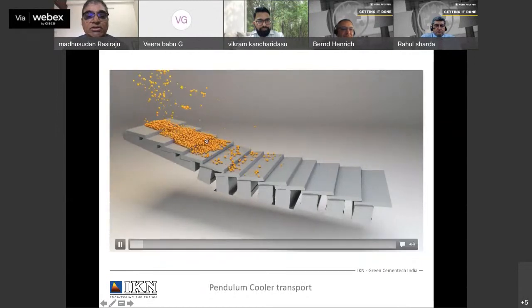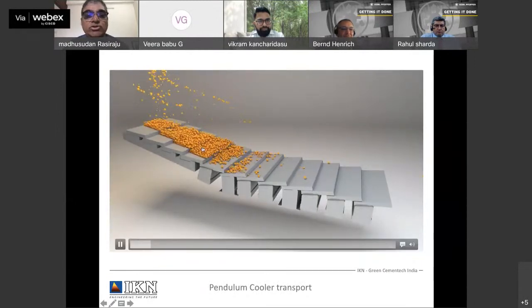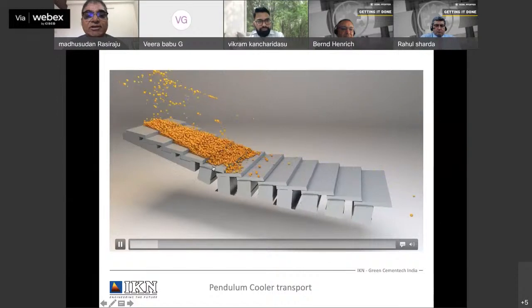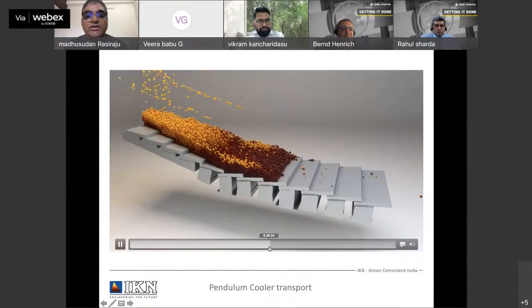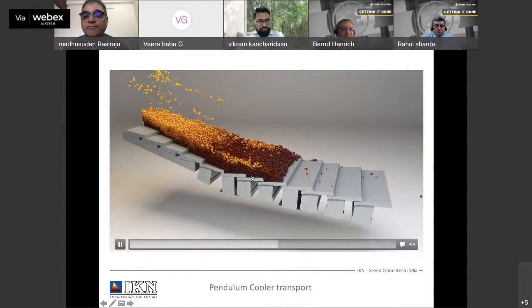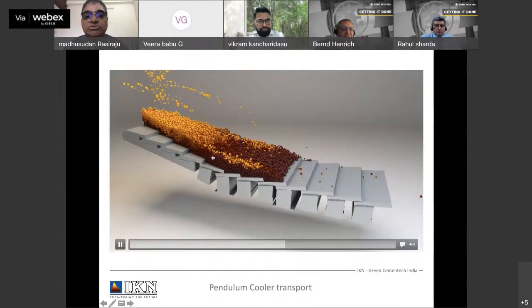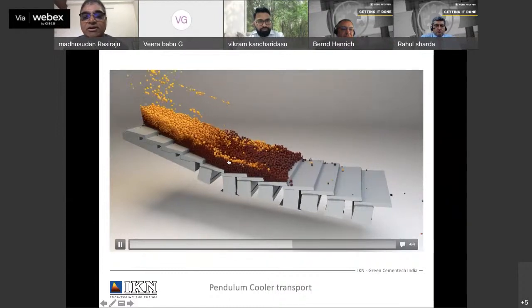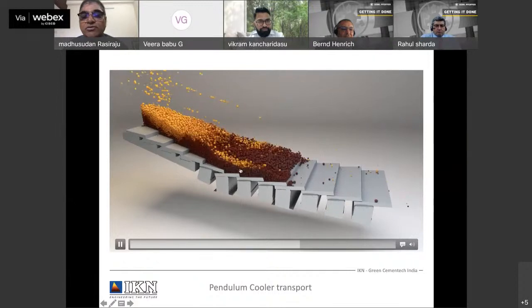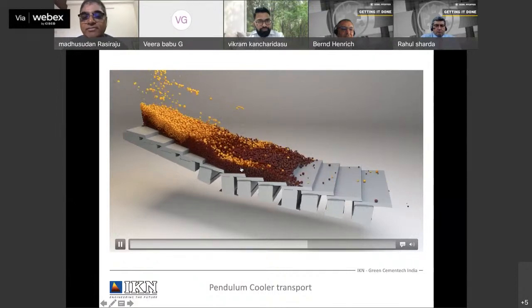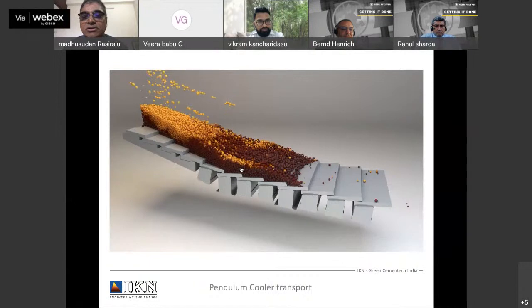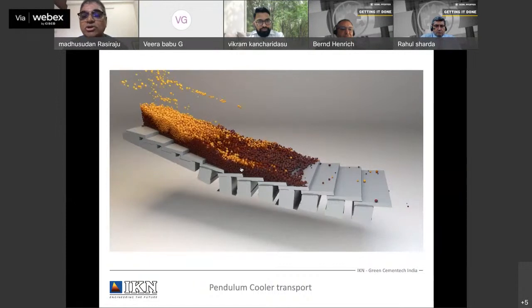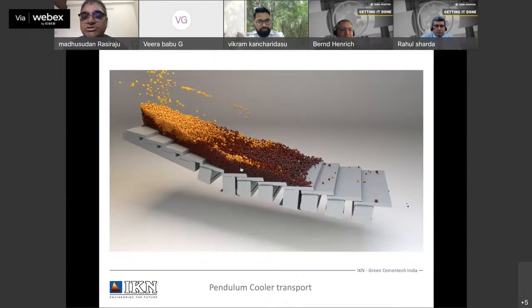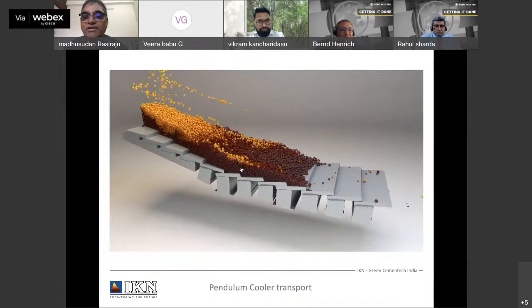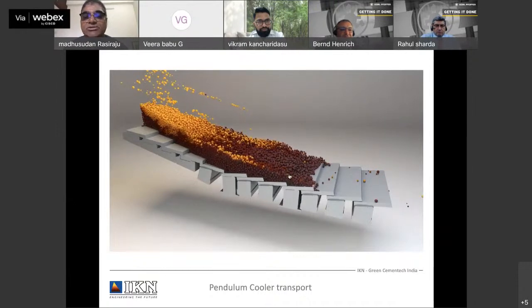And if you see here, the clinker simulation we have shown, on the fixed inlet the clinker comes in, and then when it comes to the movable section, the clinker bed is slowly received and then transported forward without any disturbance to the bed. That is the more important factor in the clinker cooler. We should not disturb the bed. The bed can be disturbed either by air or by the conveying elements. But in our case, the bed is not disturbed.